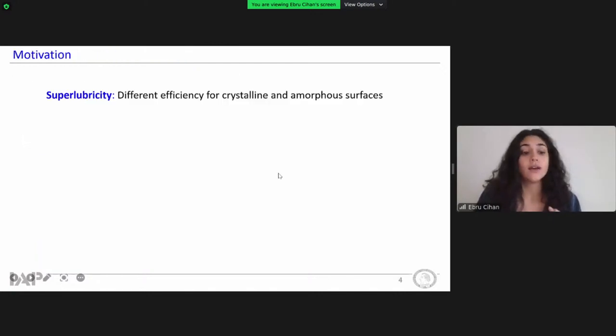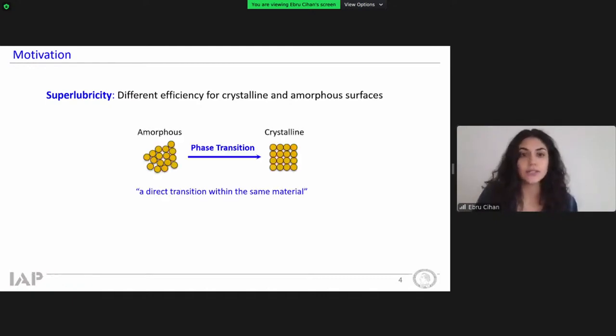In other words, we still have an open question regarding the chemical nature of the interface, and that question also needs to be answered. So this question will be the starting point of this work. Namely, to investigate the atomic origin of superlubricity, we also need to analyze the same material in two different phases. And of course, we can achieve this through a direct transition from one structural phase to another by heating, for example.